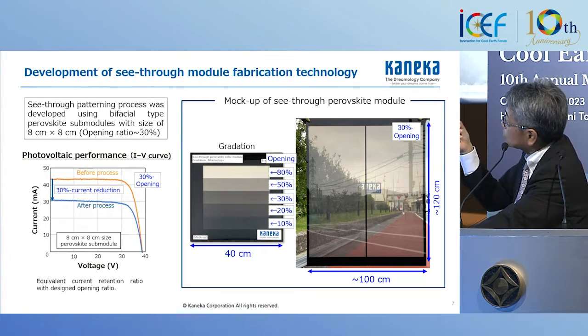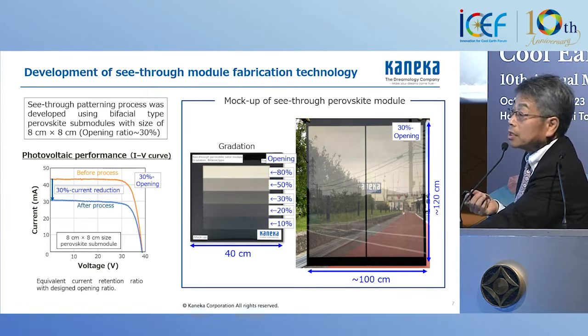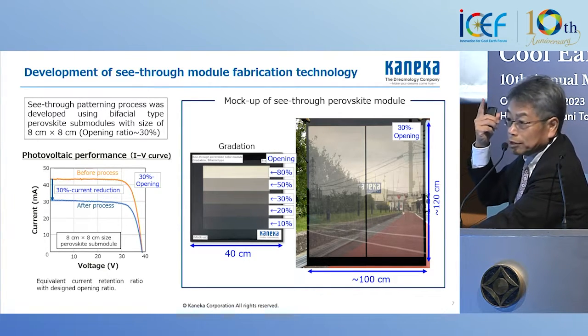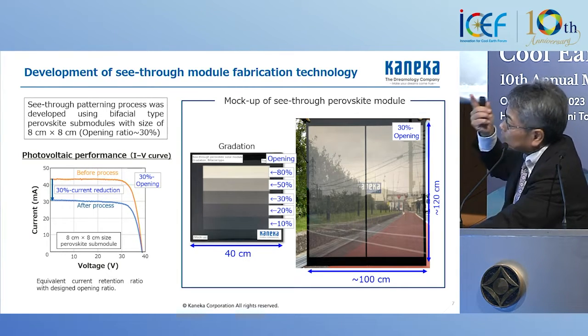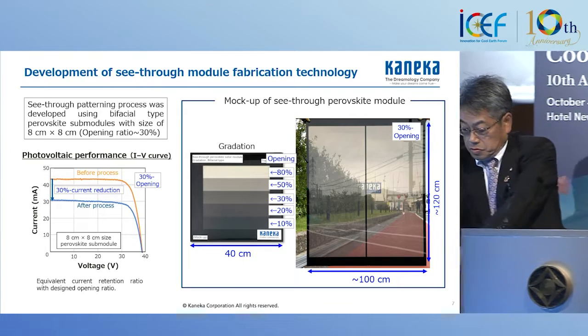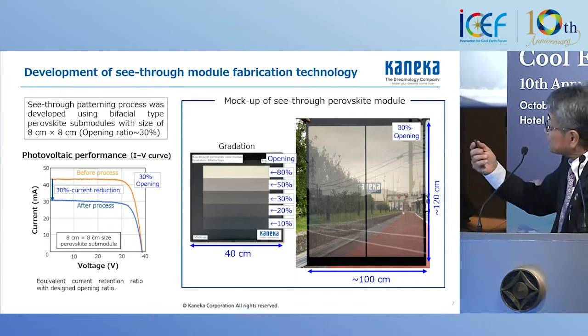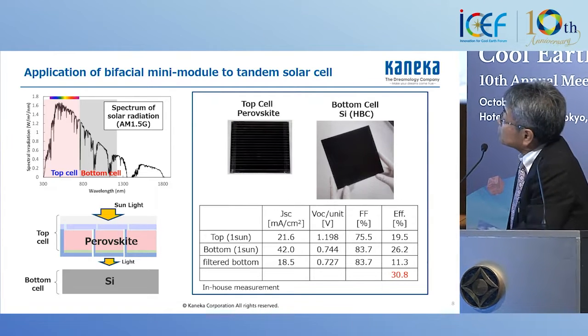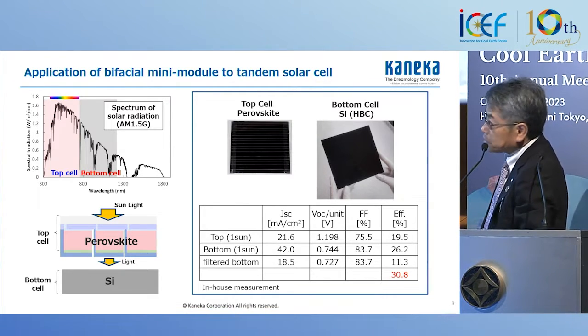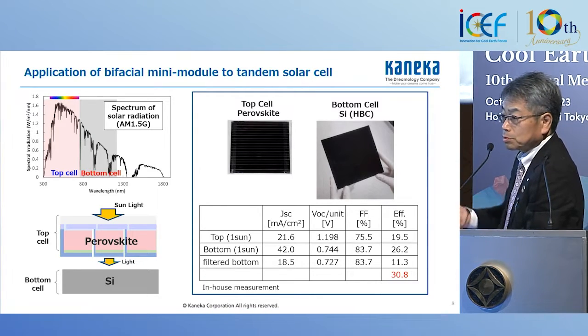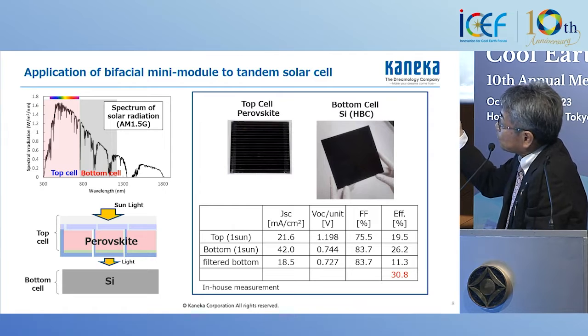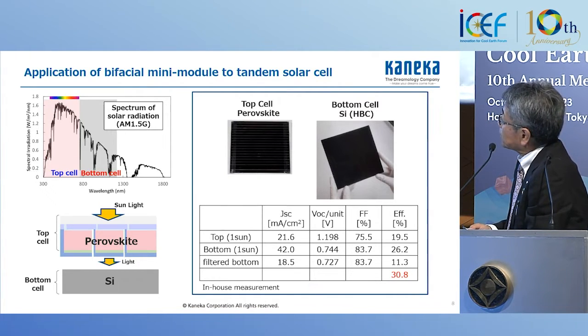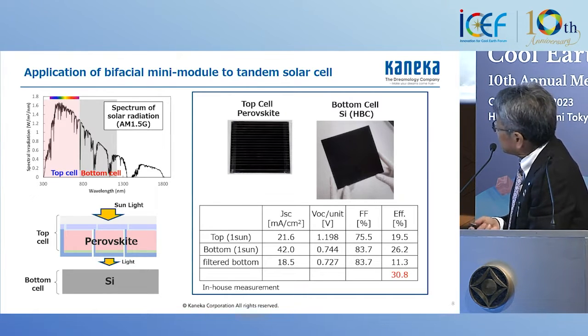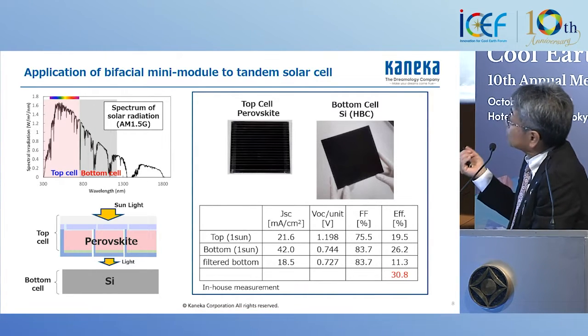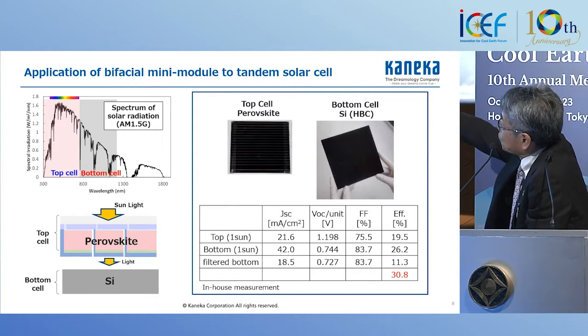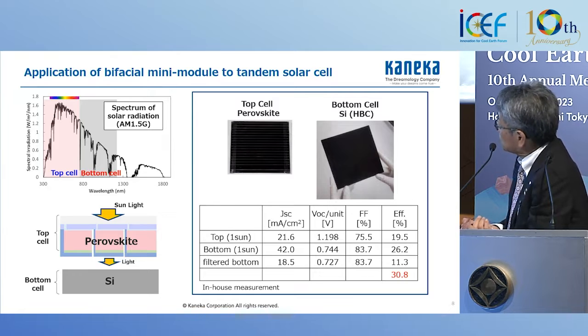We can also change the opening by laser scribing, from 10 to 80 or 90 percent, and at the same time we can make a gradation like this. This is thin film technology, and our perovskite is bifacial. We can apply that bifacial module to the combined silicon. This is one of the examples. Once we apply a top cell efficiency of 19.5, we show over 30% for this size. Actually, this time we used a very high efficiency bottom cell, 26.2.